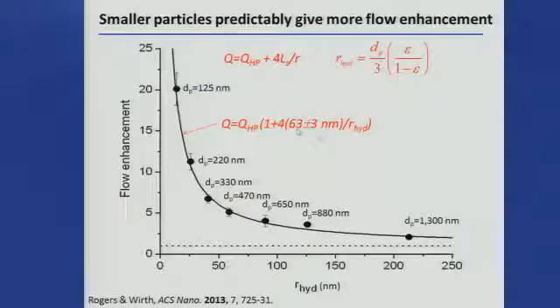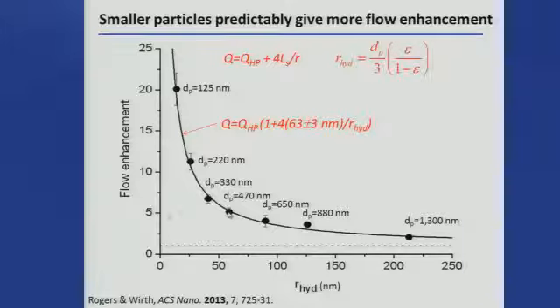This is the most precision ever reported, as far as I know, on a slip length, and so it gives you an idea for planning what you expect the slip length to be. This is with a butyl hydrocarbon chain. We get more slip flow when we use longer chains. So, for example, with these 470 nanometer particles, for the C4 we get a factor of 5. For C18 we get a 10-fold flow rate enhancement. So, whopping flow rate enhancement allows you to start using reasonably long columns with half-micron particles using commercial pumps. And so that's pretty amazing.